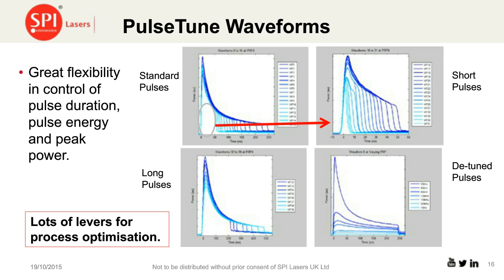We can then generate longer pulses, where you can see on the bottom left-hand graph, what happens is we're moving the energy around a little bit. So we're losing a bit of peak power, but we're adding it in terms of the length of the pulse. So we're kind of redistributing it a little bit. And this actually benefits several applications, and one of them actually is welding.